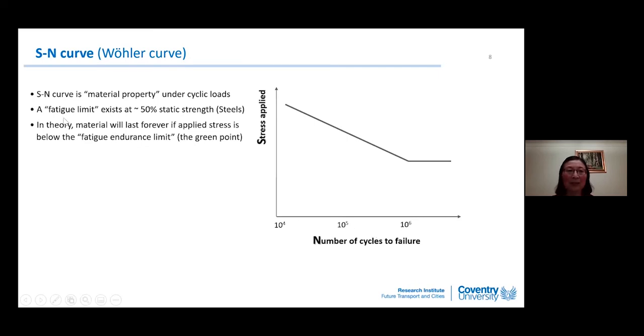of cycles to failure. There is a fatigue limit marked by the green point, and that is asymptote tendency. So the SN curve turns to an asymptote to the horizontal level. And that is true for steel alloys, for ferrous alloys. That really means if your applied stress is below the fatigue limit, there will be no fatigue. In theory, your structure will last forever.